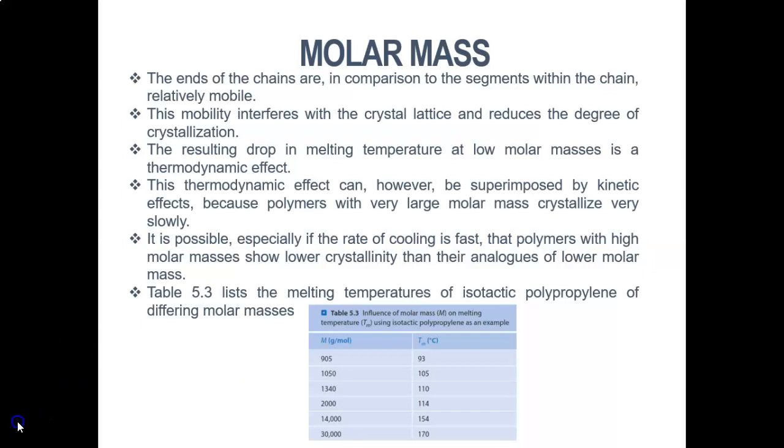Molecular weight is high. Okay, for a low molecular weight chain, they will have more chain ends per unit volume than the long chain. Thus, a higher free volume will produce a lower Tg. Okay, low molecular weight will produce a lower Tg polymer. So, practically, the glass transition temperature value of a polymer is influenced by the molecular weight by up to 20,000. Okay, same goes to Tm.